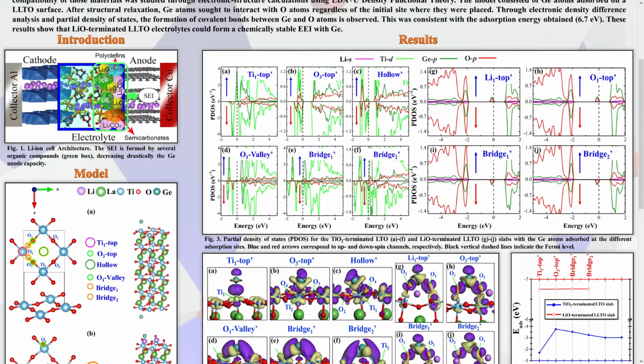For the oxygen top and hollow sites, there is strong hybridization between the germanium p and titanium d orbitals, as well as germanium p and oxygen p. Finally, for the oxygen valley, bridge 1 and bridge 2 sites, there is strong hybridization between the germanium p and titanium d orbitals, with the interaction between the germanium p and oxygen p orbitals having a less covalent character. From G to J, for lithium oxide termination, in all cases there is hybridization between the p orbitals of germanium and oxygen.